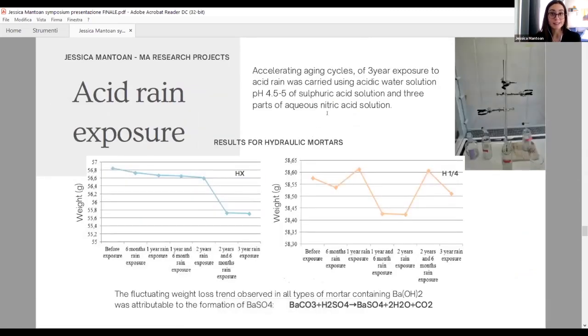Finally, I carried out my accelerated aging tests for the decay mechanisms. I started with the acid rain exposure, where I designed an aging cycle where I was able to reproduce 3 years of rain exposure of the mortar in about 10 days, using an acidic water solution having pH about 4.5, made of sulfuric acid mixed with nitric acid. And as we can see, for mortar not containing barium hydroxide, the interaction with the acidic solution creates an initial constant part and then a really sudden loss in weight.